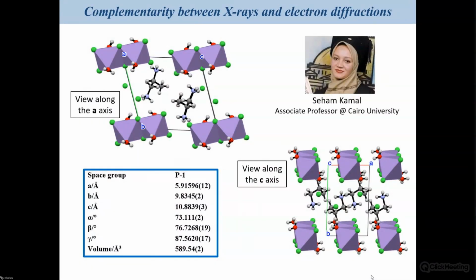So the example I want to focus on today is made of manganese octahedra. As you see on the picture, you have an equatorial plane of the octahedra, which is made by chlorine atoms, and you have an apical direction, which is occupied by water molecules. So each octahedron shares two chlorine atoms with another manganese atom. This is the distribution you have in your system. What is interesting is that for the organic part, you have propane diammonium molecules and also isolated chlorine atoms that ensure the electroneutrality of the system.